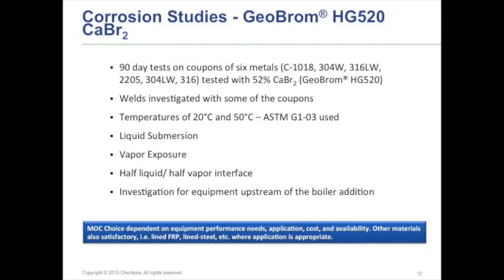When you look at the bromine additive rates, this is one that was, again, a bit of a mixed bag of information. They saw that the loading, for the most part, didn't really come in line with what you would expect, that higher was worse and lower was better. And then again, when you looked at some of the very high rates on the higher halogen coals, that was less of an issue, where they did not demonstrate corrosion. So the jury is still kind of out on that one.